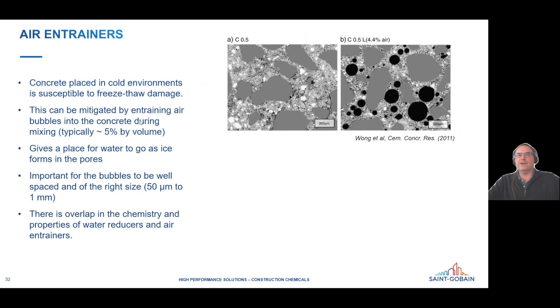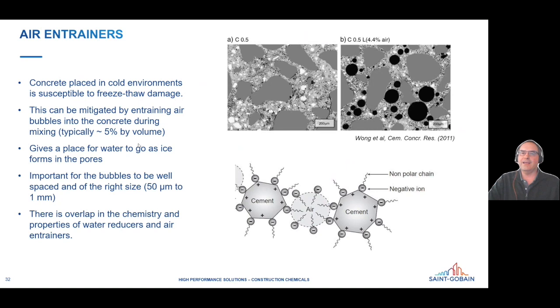And what these air entrainers do is take the air bubbles that are naturally added to the concrete during mixing, which would normally disappear quickly, and stabilize them so that they don't go away. They do that in a similar way to a PCE or a water reducer adsorbing onto a cement particle. An air bubble actually has the chemicals adsorbed onto its interface. So this air bubble, instead of diffusing out during mixing, will stabilize and remain in the concrete.